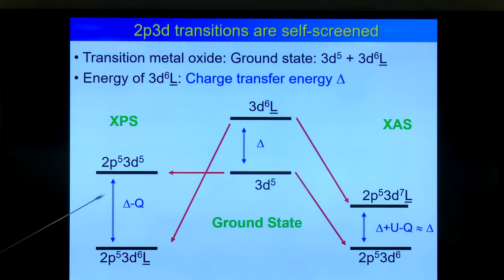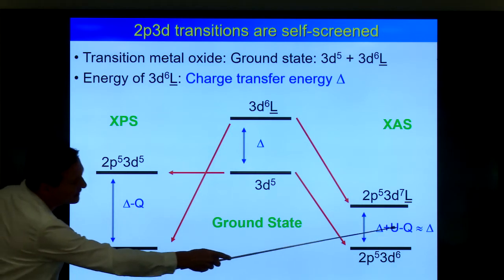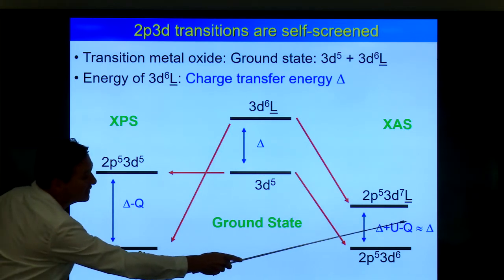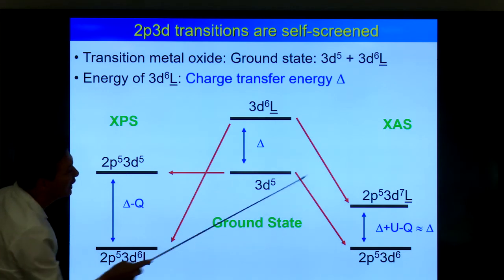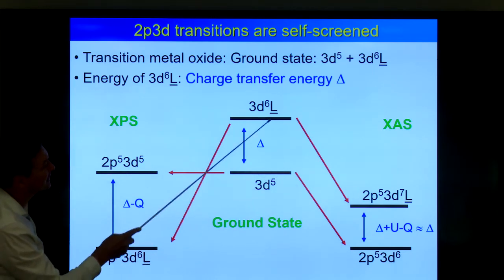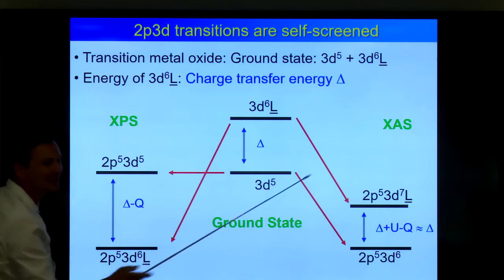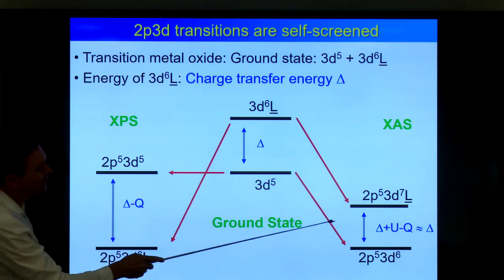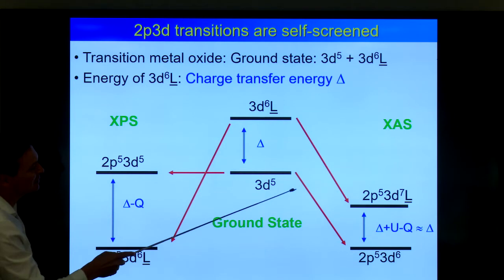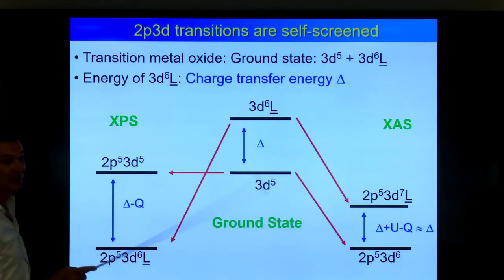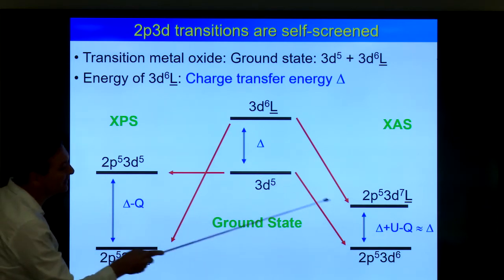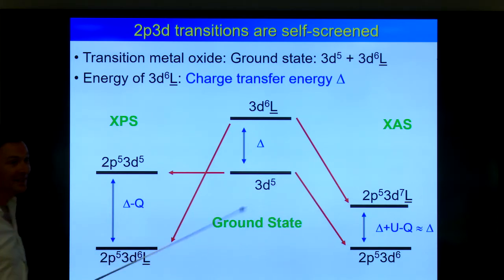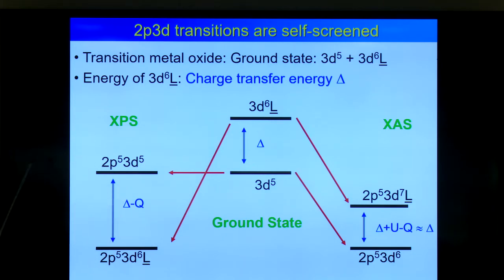Yeah. The splitting is the same. Delta is a little bit smaller in the final state because the core hole potential is a bit larger than U, but let's say initially the same. Pretty similar, right? And also the coupling is the same. Actually, again, a little bit smaller because of the localization. And if you assume that delta is the same and the coupling is the same, you get a bonding and anti-bonding combination of these two states, and the same ones there. But then mathematically, not 100% of the density goes there and 0% goes there. That's the extreme case. In reality, something like 90% goes to the bonding one and 10% to the other. So you have a weak charge transfer satellite, but it's something like 10%.